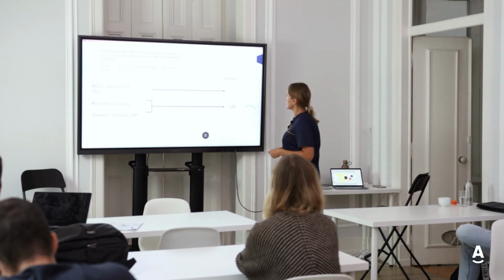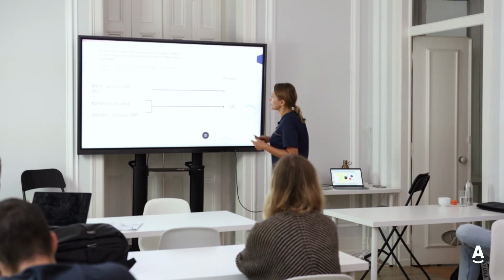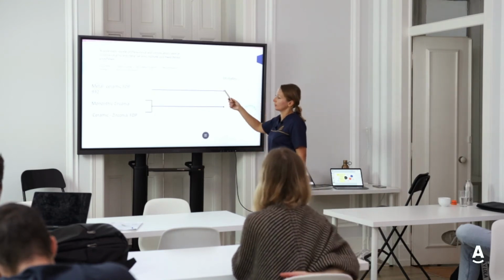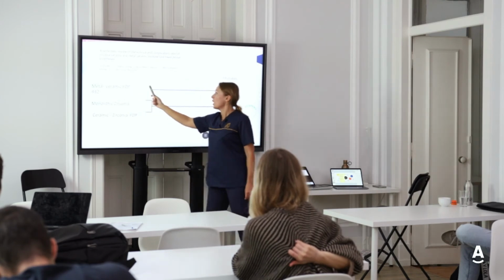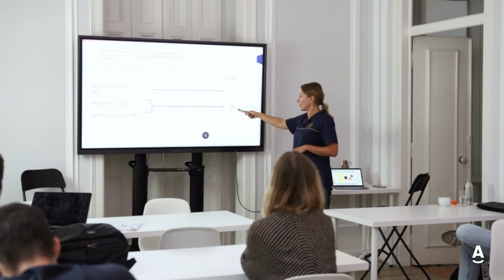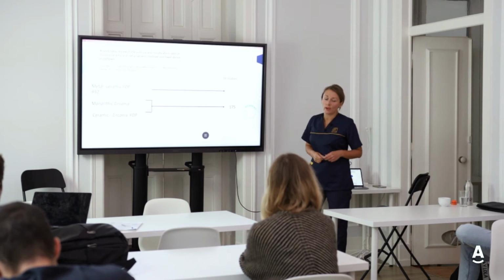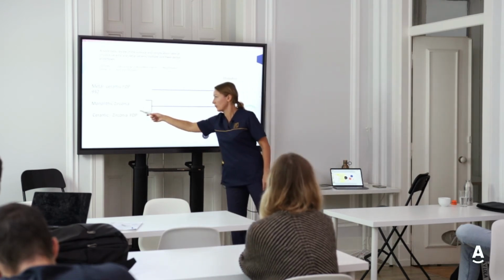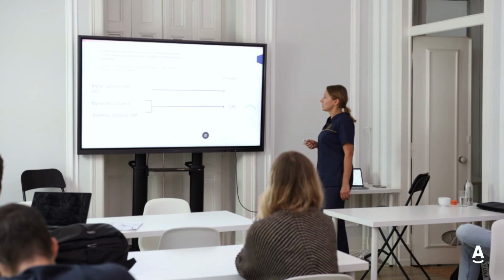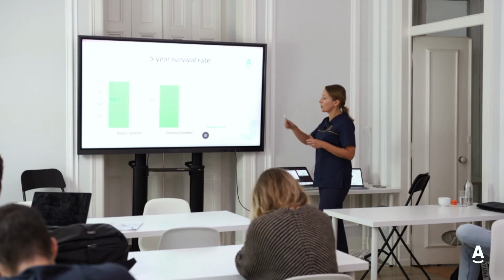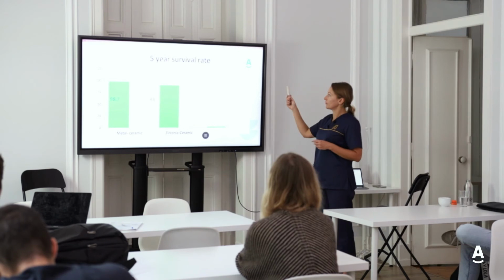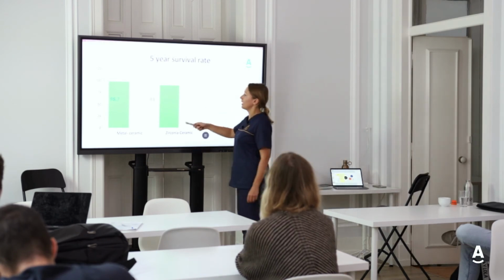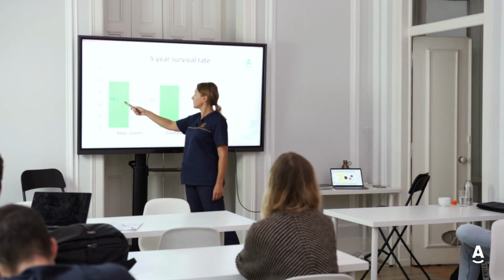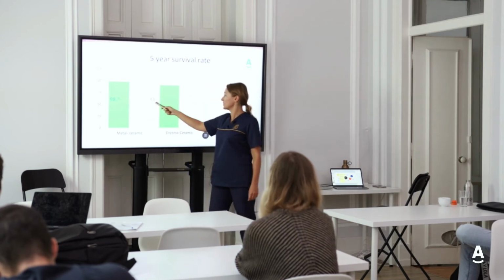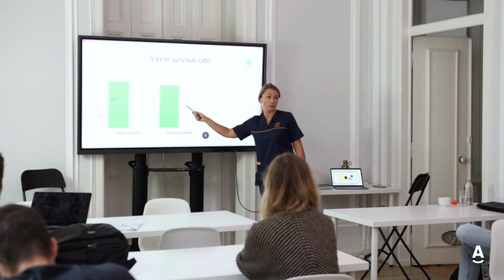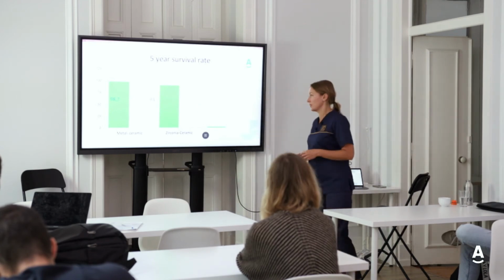So these studies, it's a review of 90 studies actually, and they were comparing 932 metal ceramic units, comparing with 175 units, monolithic as well as veneered ones. So what was found is that in both of the groups, the 5-year survival rate were high and quite comparable, 98.7% for metal, comparing to 93% for ceramics.